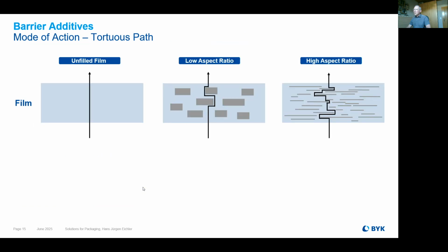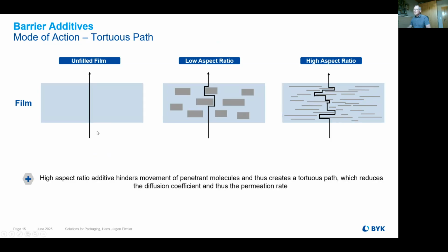With that said, I will now give you an idea of how the mode of action works with this mineral. Of course, the simple way is you have your film and your gas passing through without any big issues, coming from this side and going over to that side. So no real barrier properties. If you have minerals like calcium carbonate or talc, they have a low aspect ratio. What happens if you disperse them in the matrix? You see here, these gray parts are the minerals, and the gas is passing around them. And of course, if you have a product with a high aspect ratio, the gas needs to take longer ways around the particles. That's exactly what our mineral is doing. If it is well dispersed in the matrix, it increases the barrier properties due to the increasing tortuous path.